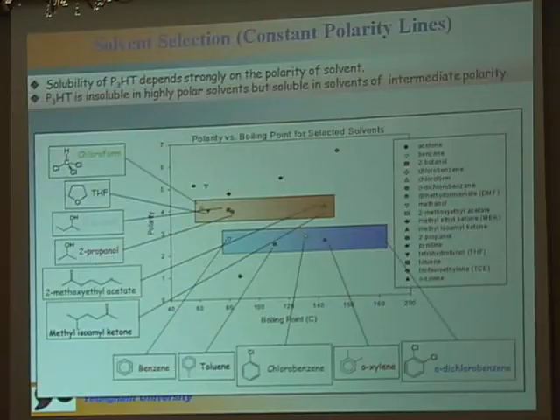You know, for making the composite solution, we tried many different solvents to better make the composite solution. The polymer depends strongly on the quality of the solvent. P3HT is insoluble in highly polar solvents, but soluble in solvents of intermediate polarity. You can see in this example: chloroform, toluene, chlorobenzene, and dichlorobenzene.